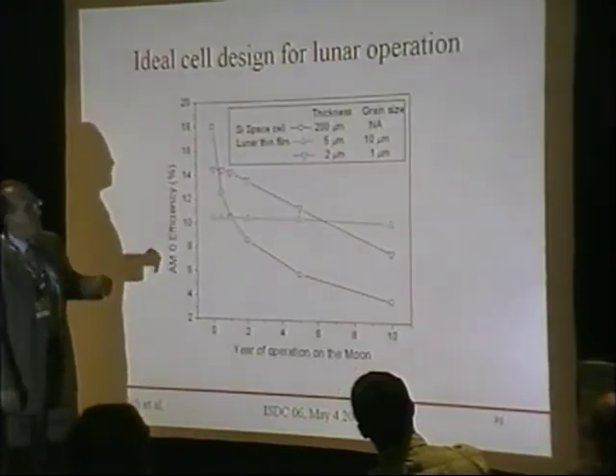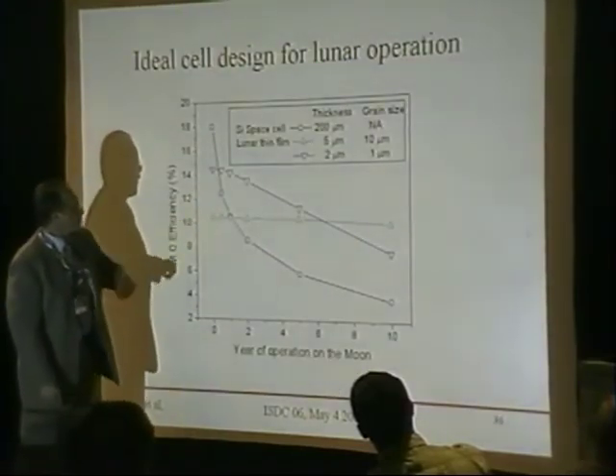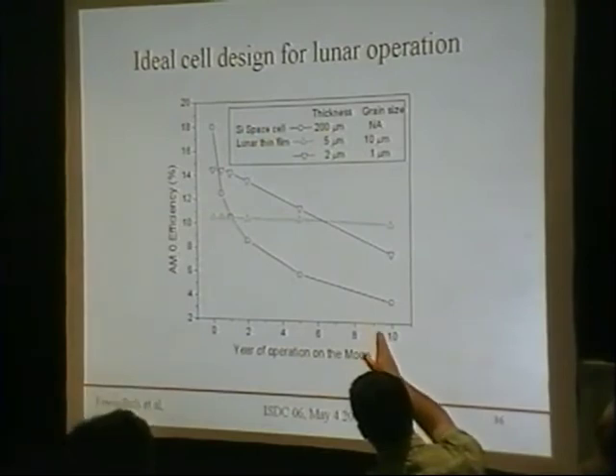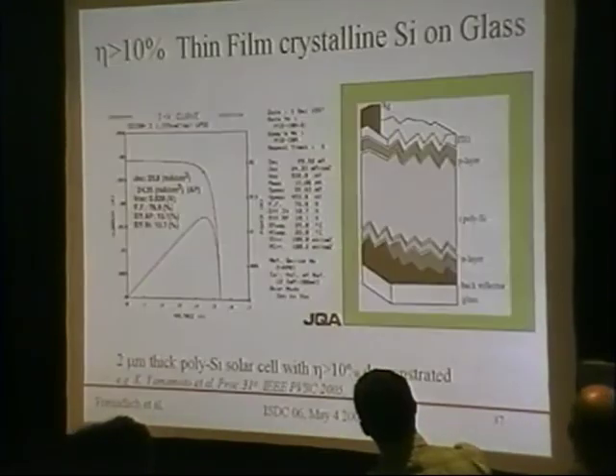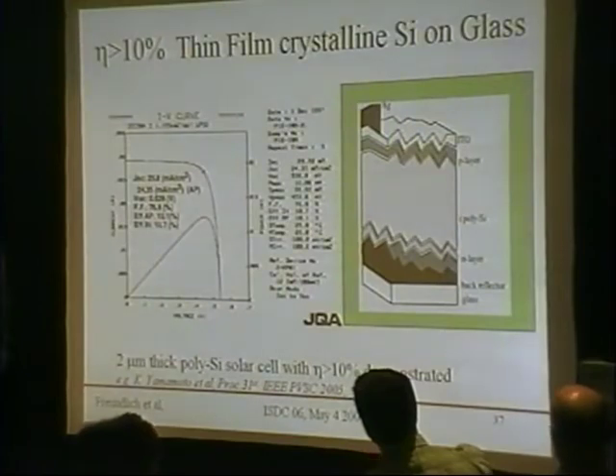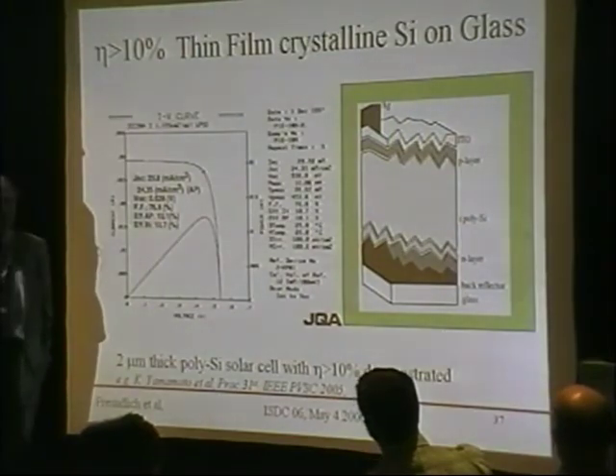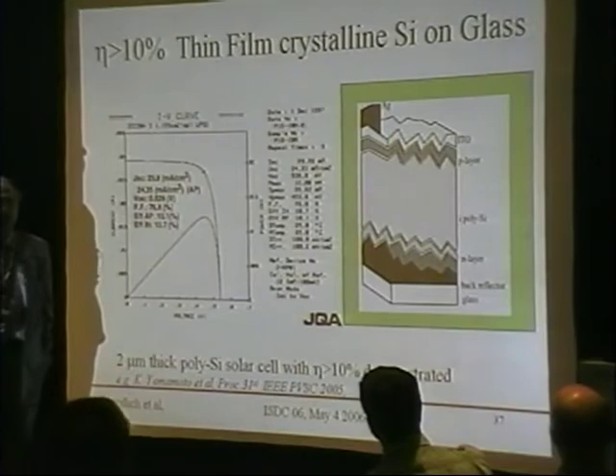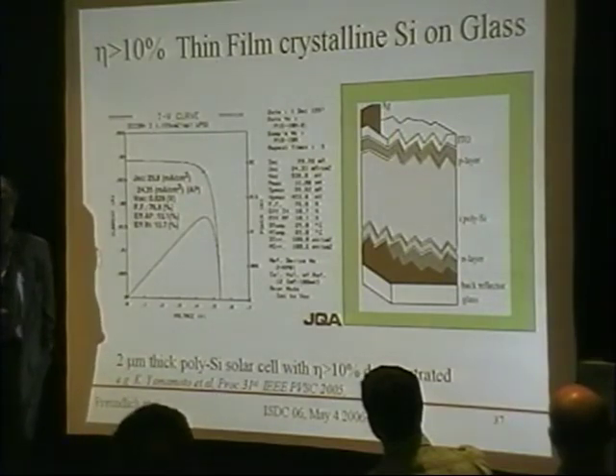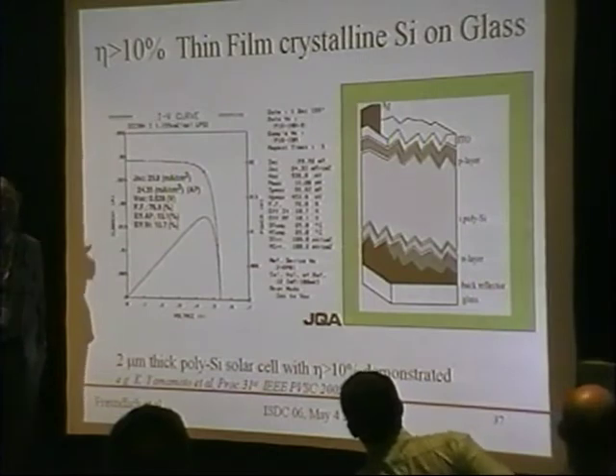That cell was calculated to be 11%. Next is an experimental result. Plus, if it's a thinner cell, then I would think it would use less material to manufacture. Absolutely. For us, the process goes faster. If we have 2 micron, it's going to take us 1 hour. If we have 5 micron, it's 2.5 hours. So the production rate goes up.